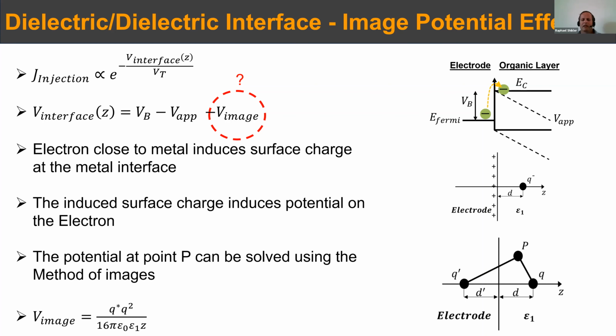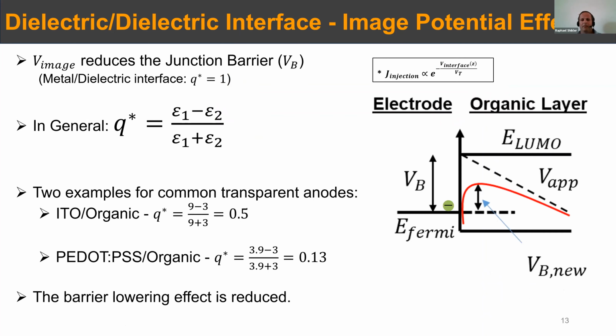Now, in metal, this Q star is 1. However, in a dielectric, this is not true. For example, in ITO, the dielectric constant is 9. If you go to PEDOT, then it's 3.9. So what is the implication of that? If you look at the interface between this electrode, let's say ITO, and the organic layer, you need this Q star, and Q star can be calculated using simple electrostatics to be equal to epsilon 1, which is at the electrode side, minus epsilon 2, divided by the sum of them. So instead of having Q star equal 1 in metal, you go down to 0.5 in ITO, which means that the reduction in the barrier is smaller. And if you use PEDOT:PSS as an interface instead of ITO, this is supposed to reduce it even further.